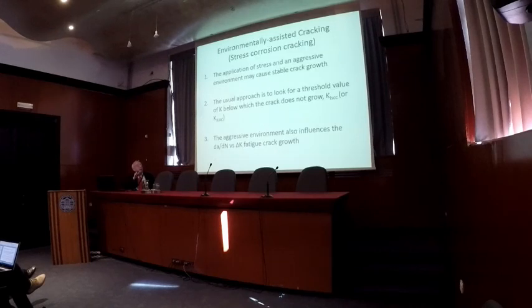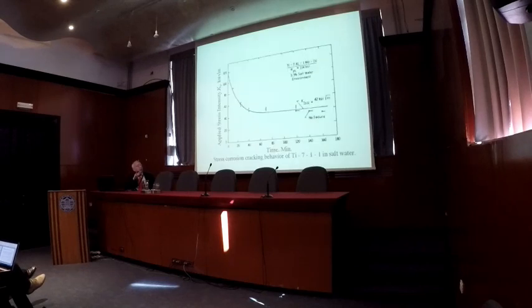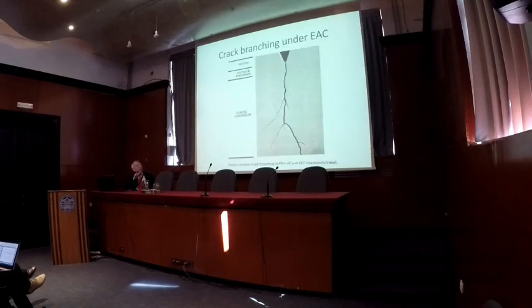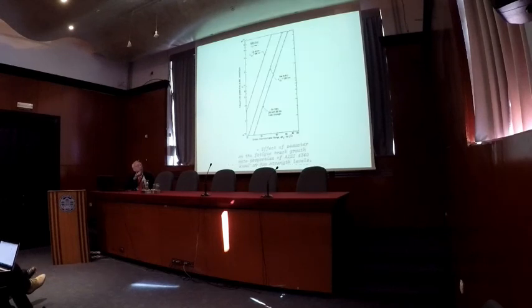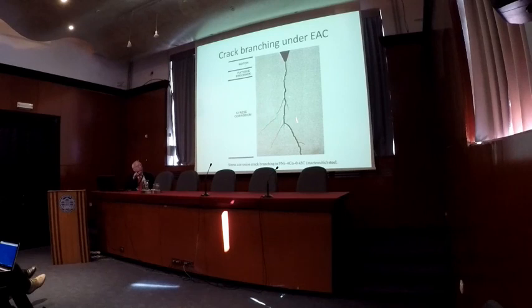And the aggressive environment also can influence fatigue crack growth. So here's just a picture of what you often get in stress corrosion cracking or environmentally enhanced cracking, which is called crack branching. If you see crack branching in your specimen or structure, you might think then that that's an indication of environmental problems.